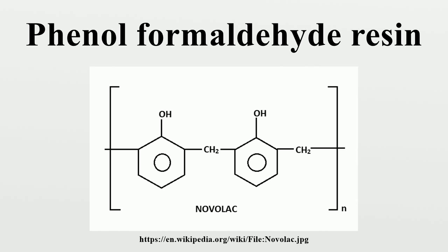Resoles are referred to as one-step resins as they cure without a cross-linker, unlike novolacs, which are two-step resins. Resoles are major polymeric resin materials widely used for gluing and bonding building materials. Exterior plywood, oriented strand boards, and engineered laminated composite lumber are typical applications. When the molar ratio of formaldehyde to phenol reaches one, in theory every phenol is linked together via methylene bridges, generating one single molecule and the system is entirely cross-linked. This is why novolacs do not harden without the addition of a cross-linking agent, and why resoles with F:P greater than one will.